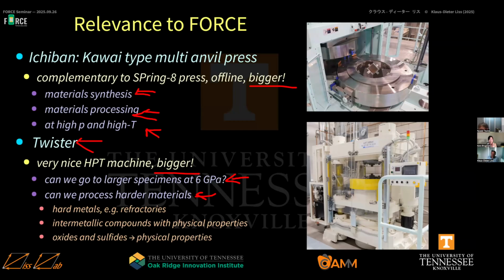Okay, then last question. Ichiro Mori says, I think that neutron diffraction takes longer to accumulate a single profile than XRD, even with a spallation source and compared to synchrotron X-ray. But how much strain and stress resolution does it have? That's right. With neutron scattering, we cannot do micro-beam diffraction because the beam is much larger, in the many-millimeter regime. And even a full disk, so we have placed the full disk in the neutron beam at J-PARC in Japan. The counting statistics is weak, but what we have is good peak profile resolution.